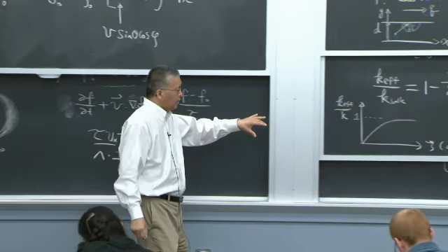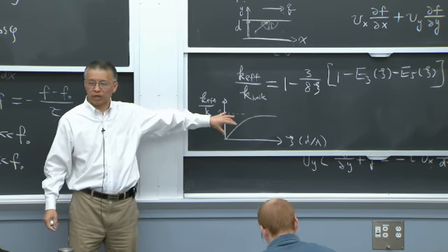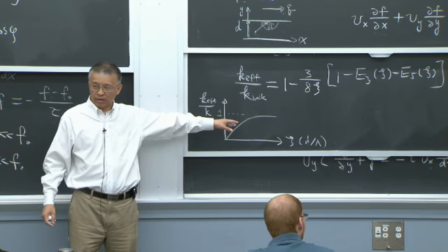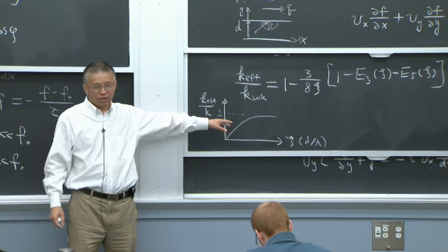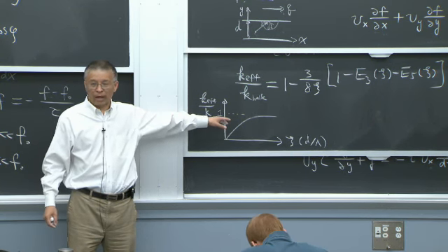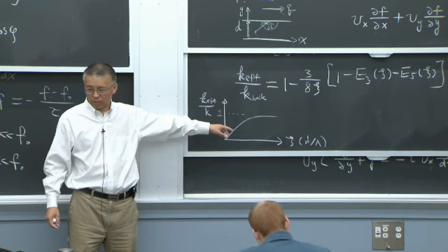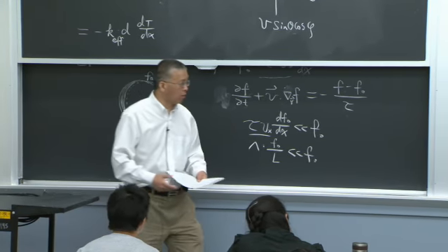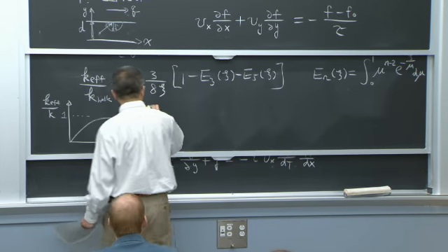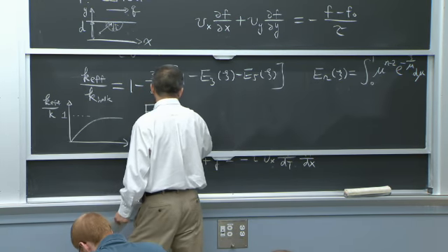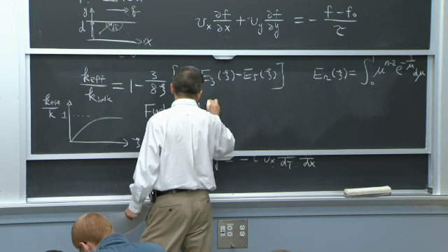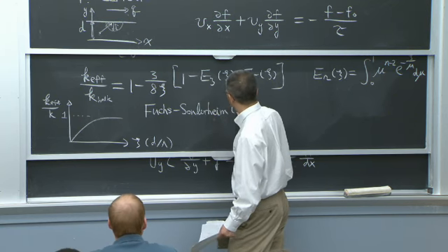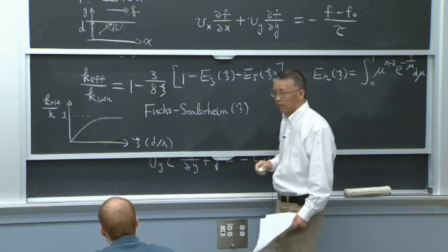So for nanostructures, those properties eventually should go back to bulk when you make it thick enough. And if you have a theory, you sanity check, right? When you go back to the bulk thickness, do you get the bulk properties? This solution is also called the Fuchs-Sondheimer solution.